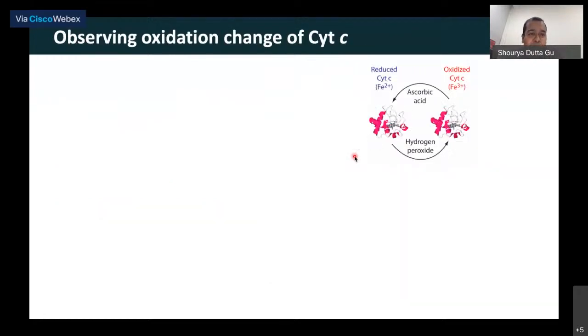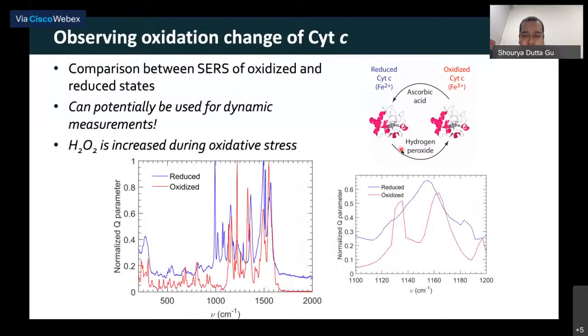So now, can we do some kind of diagnosis with this? Now, the way that the diagnosis works is we exploit the property of these cytochrome C molecules that we have on those particles, right? Now, cytochrome C is a very interesting molecule because, as I said, it has this redox reaction kind of feature. Now, one way of oxidizing it is using hydrogen peroxide. Now, hydrogen peroxide is a chemical that also is produced in the body when you have a lot of stress, right? So whenever you have stress, the level of hydrogen peroxide or reactive oxygen species actually goes up. So by measuring how much of reduced and oxidized cytochrome C you have, you will be able to tell whether you are in a stressed condition or not.